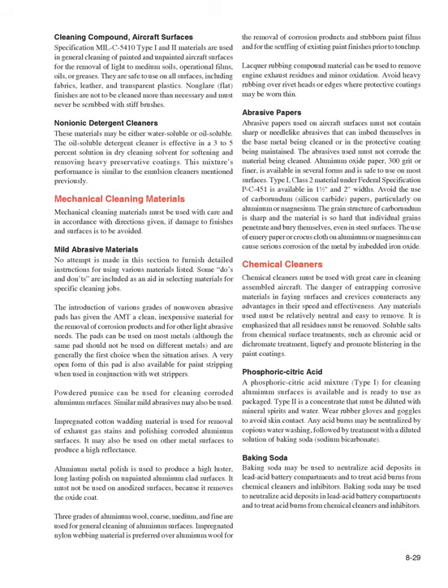Abrasive papers. Abrasive papers used on aircraft surfaces must not contain sharp or needle-like abrasives that can embed themselves in the base metal being cleaned or in the protective coating being maintained. The abrasives used must not corrode the material being cleaned. Aluminum oxide paper, 300 grit or finer, is available in several forms and is safe to use on most surfaces. Type I, Class II material under Federal Specification P-C-451 is available in 1-1/2 inch and 2 inch widths. Avoid the use of carborundum, silicon carbide papers, particularly on aluminum or magnesium.